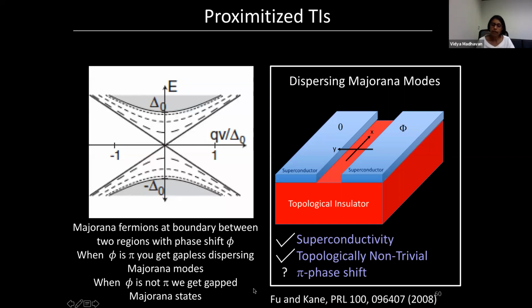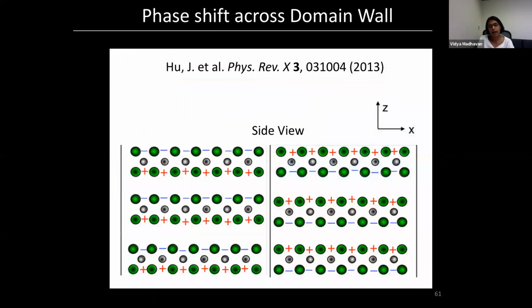So what do we have? To realize these propagating states, you need superconductivity. You need the material to be topologically non-trivial. I've shown you that we have both in this iron selenium tellurium. And finally, you need a region where on one side you have one phase in your superconductor, and on the other side you have a different phase. And ideally you want to have a pi phase shift. So astonishingly, as it turns out, this material gives you that, just like that.